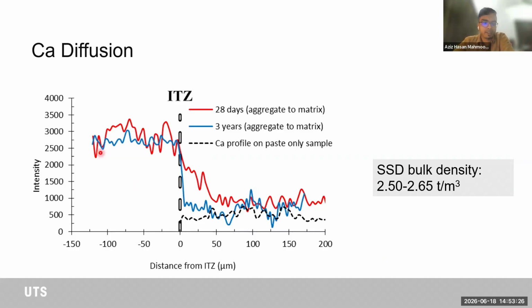The other thing that we were worried about is the free lime associated with the steel furnace slag. So we ran a testing which is EDS. So it's a sort of a spectroscopy, but the main point here is we can see the calcium profile on it, right? And so this bit here is the aggregate, and that's your paste. So initially, after 28 days, we could see a gradient in the calcium profile, which means that the extra or free lime was moving from the aggregate into the paste matrix. And after 3 years, there's a sharp drop of calcium, which means that all the free lime has been absorbed within the paste matrix here. And the dotted line here is the reference for us. So that's on the paste sample only.